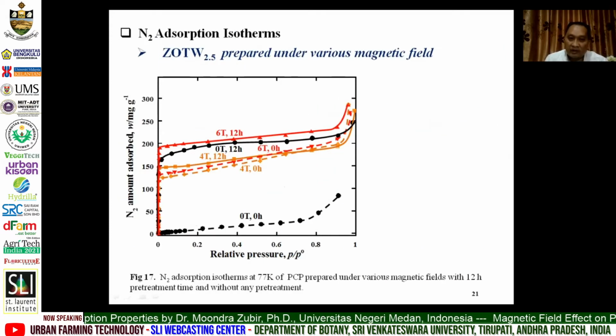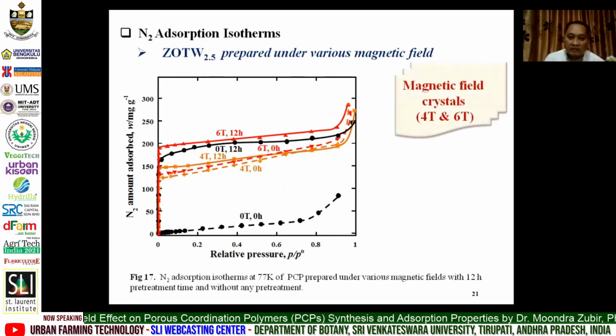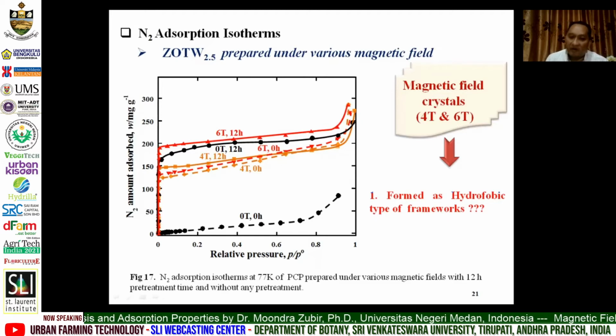Now, if compared with the other magnetic fields, the same phenomenon is shown for the magnetic field crystals. For 4 Tesla, without the pretreatment temperature, the pore of the crystal is already formed. So we consider that these magnetic field crystals, especially 4 Tesla and 6 Tesla, form as a hydrophobic type of framework, because without pretreatment temperature, the pore formation already occurred in this crystal. If compared with 0 Tesla without pretreatment temperature, in this 0 Tesla crystal we should remove the solvent first to form the framework of PCPs.